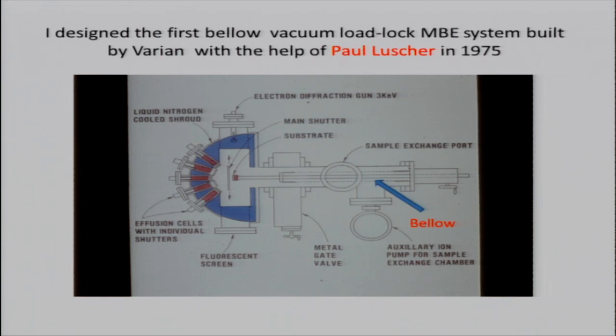And then here's the big bellow. Well, what I did is I had that sample mounted in the center here, that rod here. We first pull out this to the end. The gate valve is closed. We mount a new sample in there. After the pumping with auxiliary ion pump over here, then when we pump down to 10 to minus 7 or whatever, and then we open the gate valve, inserting this big bellow rod. It's really very ugly, to send it to the center there for the growth.